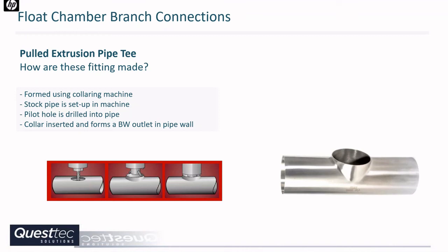And at Questec, we actually worked on having this capability, but as we were engineering this capability, we realized that it's really not a good method. Mainly due to the machines that these manufacturers have. They were really designed for Schedule 10 pipe, and what they're doing is pulling that Schedule 10 pipe into a butt weld, resulting in a thinner wall at that curvature of the pipe.